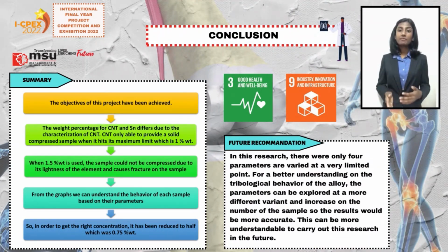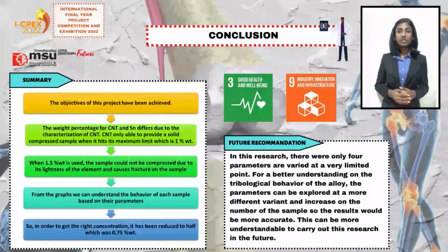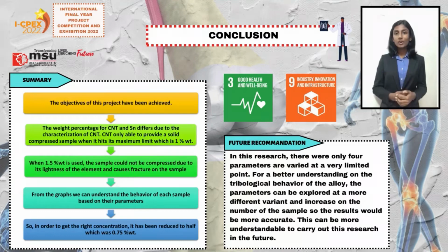The speeds that have been used are 10 Hz and 20 Hz, whereas the load is 0.5 and 1 kg. There were a total of 40 samples being experimented. The experiment was done based on the design of experiment for all the variables. As for the second objective, the effect of the binary additions on the microstructure and tribological behavior of titanium nickel shape memory alloys have been systematically investigated by obtaining the results on the wear behavior.